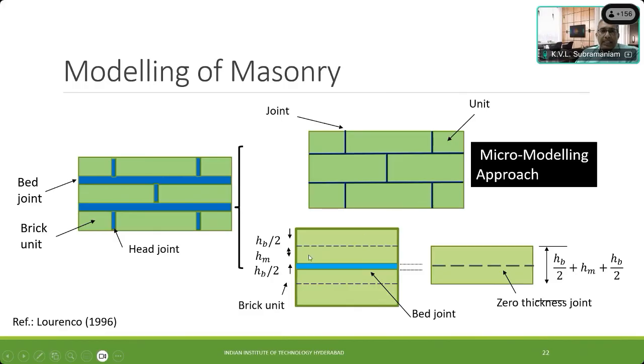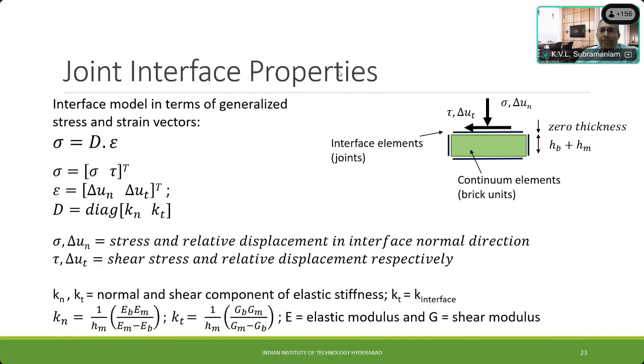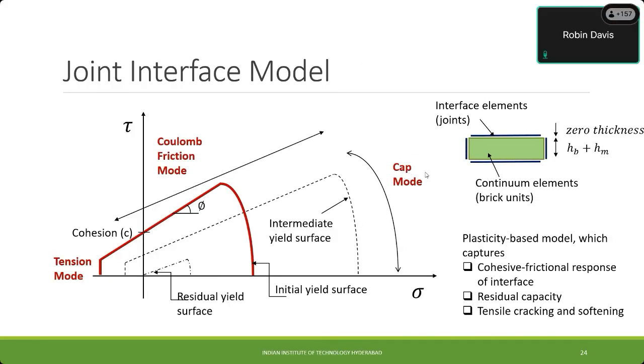This is basically a model developed by Lourenço in 1996, the micro modeling approach. It's basically a pseudo plasticity and fracture kind of approach. But it requires a lot of material parameters, and those we were able to get from our material level tests. This is the plasticity model that they have. It's basically a Mohr-Coulomb type failure surface with a tension cutoff and a compression cap.